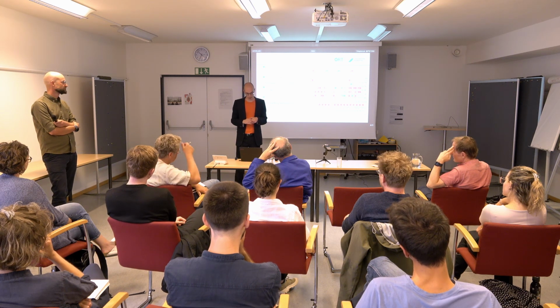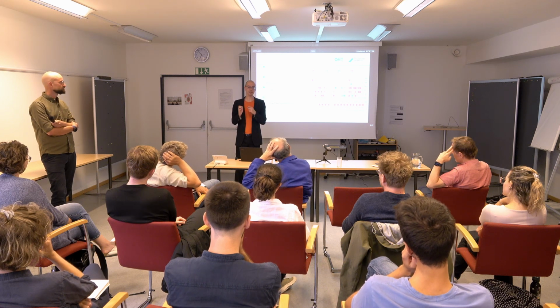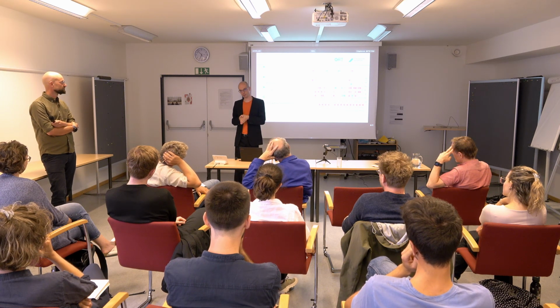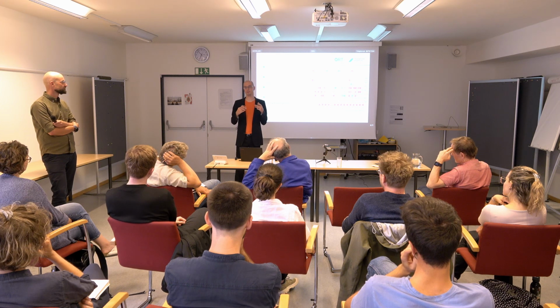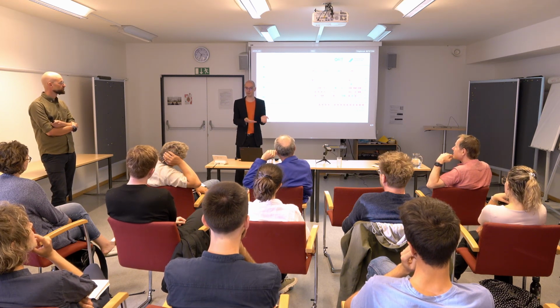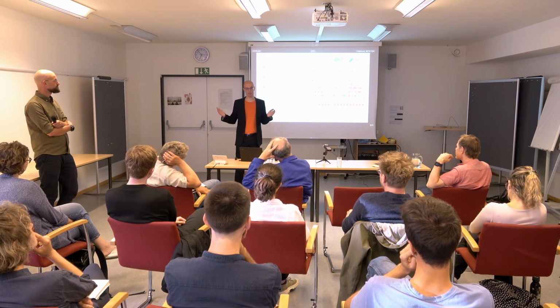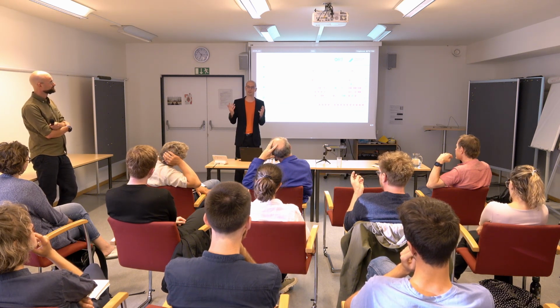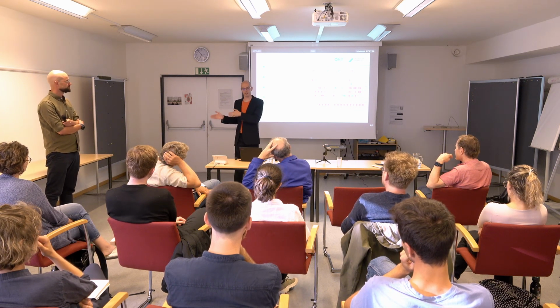There's one more thing to keep in mind. Many of the greenhouse gas emissions for primary production are not energy related. For example, for steel, a lot of the emissions come from coking coal being oxidized to carbon dioxide, so coking coal is a reduction agent for the production. We hopefully will replace that, maybe partially or fully, with hydrogen or something similar, so that you have a non-carbon-based reduction agent.